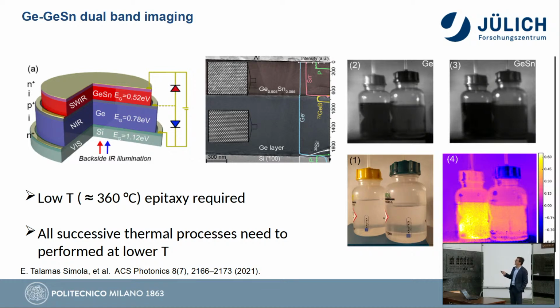So you see the quality of this epitaxial germanium, and again, we performed the experiment to tell what's in this bottle, which kind of solvent it is. The problem here is that this technique can be performed only on a full wafer. So you have to deposit your germanium tin everywhere. And if you consider the processes required to obtain a device, epitaxy is very typically the first step. So the first thing you do is deposit your germanium tin layer.